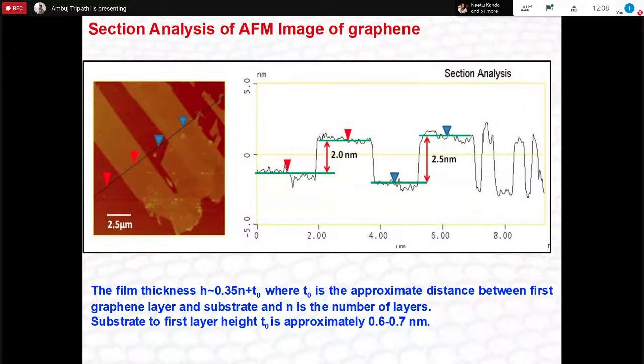So of course you always get this idea from looking even with an optical microscope, you can see with this color, so that gives you an idea. But this is an AFM image, so this is the actual measurement of the thickness. Here you are trying to see the height, and as you can see, this thickness generally varies. Each layer is around 0.35 nanometer, so 3.5 angstrom. But the very first layer, because it is between the substrate and the surface, starts at around 6 or 7 angstrom, so 0.6 or 0.7 nanometer, and that is how you can get the number of layers. So you can find the samples, and then you do this irradiation work on that.